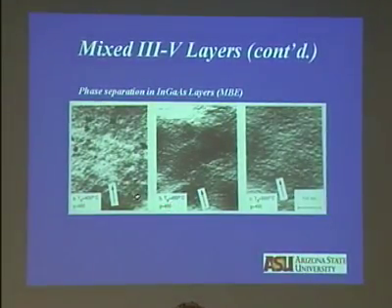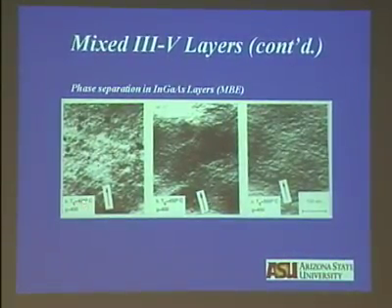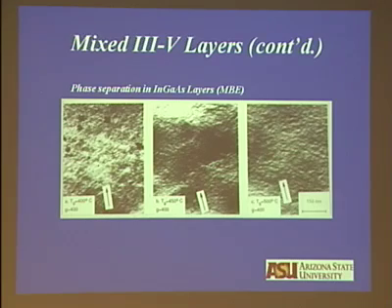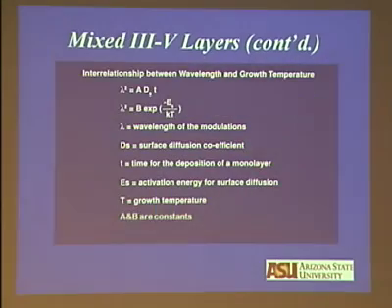These are the reflections we are using, at 400, 450, and 500. And you see the speckle structure in all of these layers. And we can determine the wavelength, again, from the position of the satellites. And those results we can explain. But let me first give you the development, how the wavelength develops, how the amplitude develops in these materials.